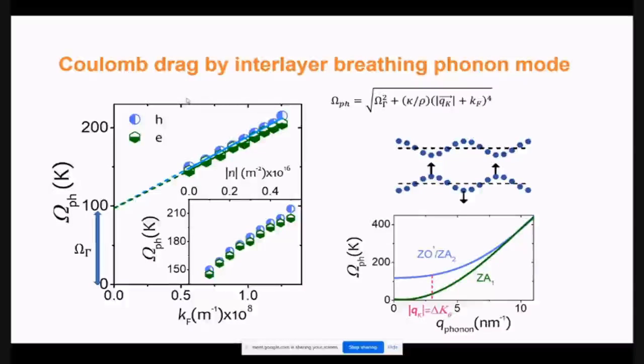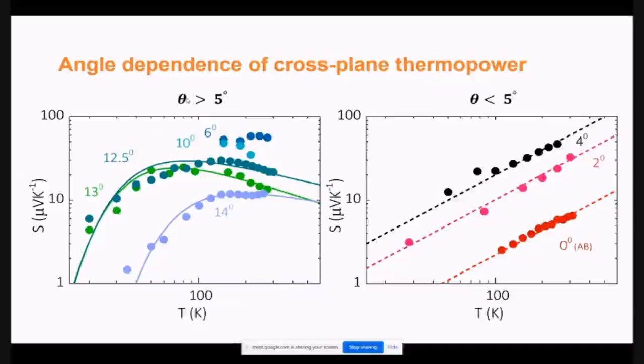Coulomb drag also does the same thing. We have phonons which are a number gradient, and that leads to potential difference. What we are looking at here is really phonon drag at 0.3 nanometer distance. Okay, but that's not the entire story, and this is something which hopefully will come up very soon. We see these phonons are dominating the show only when the angle between the two layers is more than 5 degrees or so.